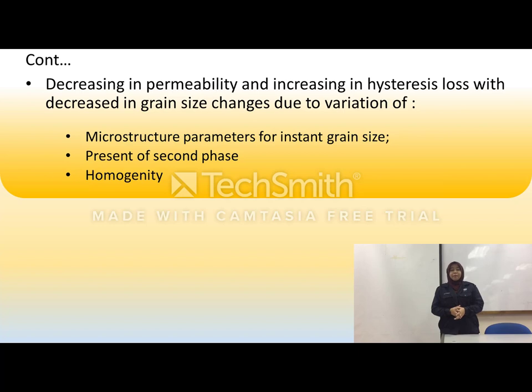So the decrease in permeability and increase in hysteresis loss with decrease in grain size changes due to variation of, first, microstructure parameters for instance grain size. The second one is the presence of a second phase. And the third one is the homogeneity. So the values of permeability and hysteresis loss will be contradictory to each other. Converting material from multi-domain to single-domain phase needs a larger field to reverse magnetization, which will increase the hysteresis loss. The smaller the grain, the smaller the permeability and the larger the hysteresis loss, or vice versa.